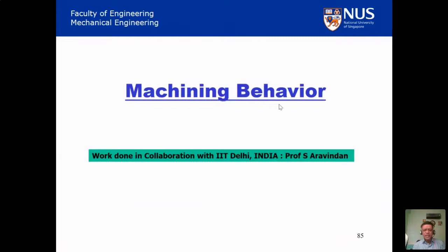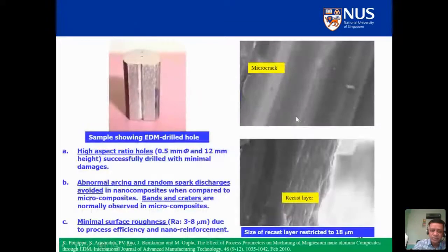Now, to put any material into application, it needs to be machined. So your material also has to be machinable. And some of the initial work we did was with researchers at IIT Delhi, Professor Aravindan. We sent our samples to them. They investigated the machining of high aspect ratio holes, and their observation was, yes, you can make these holes. They did not observe any abnormal arcing or random spark discharges, and the surface roughness was also quite acceptable in their work.